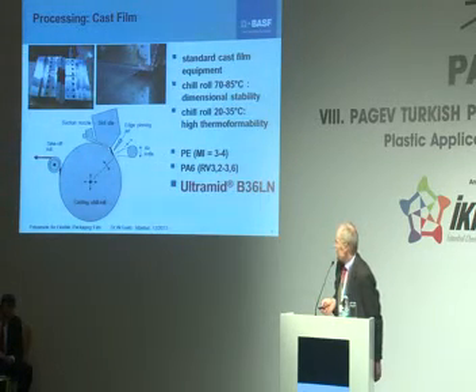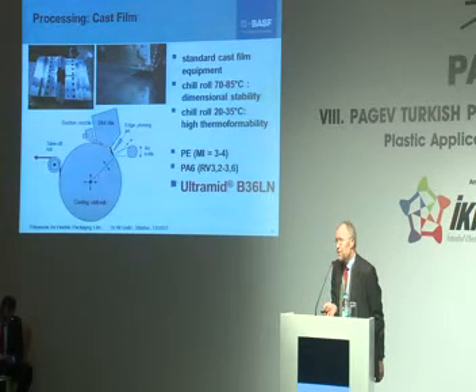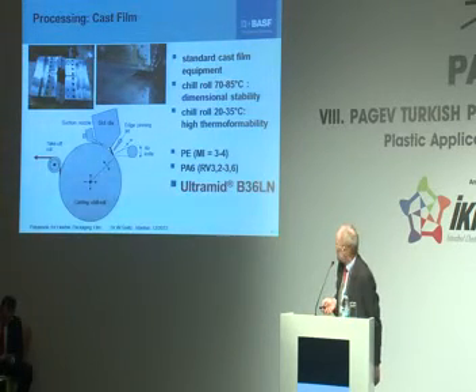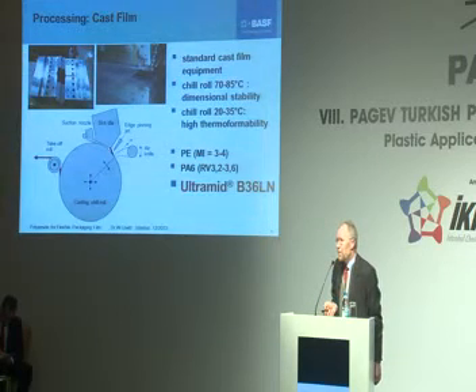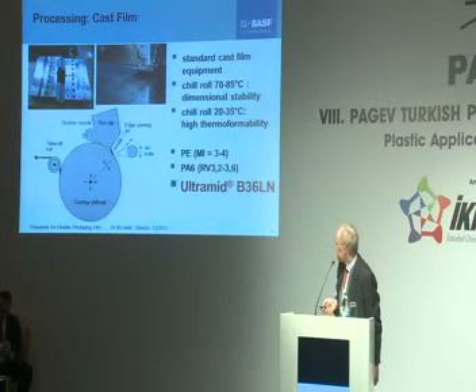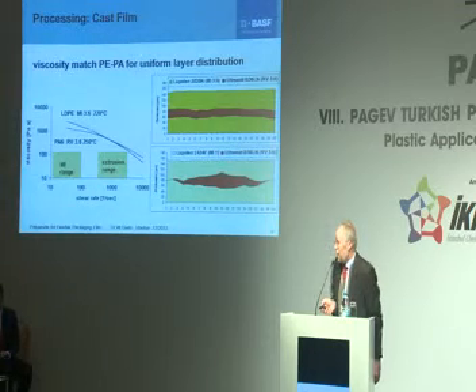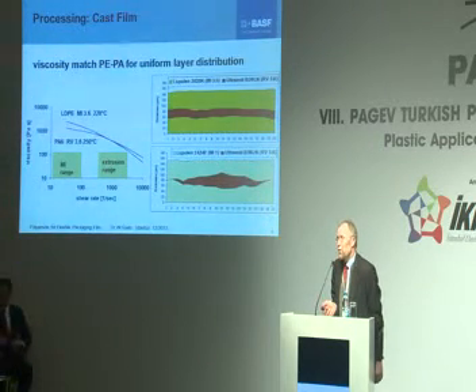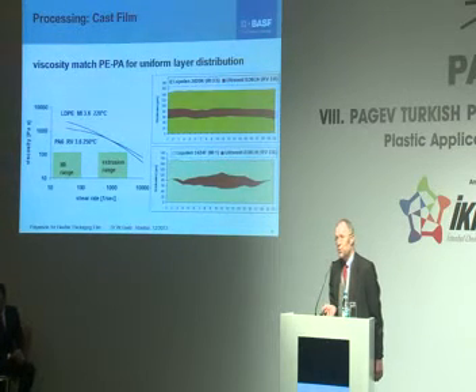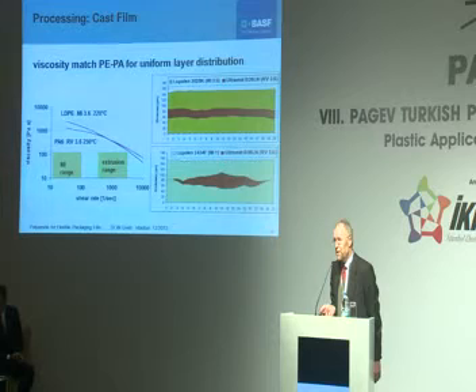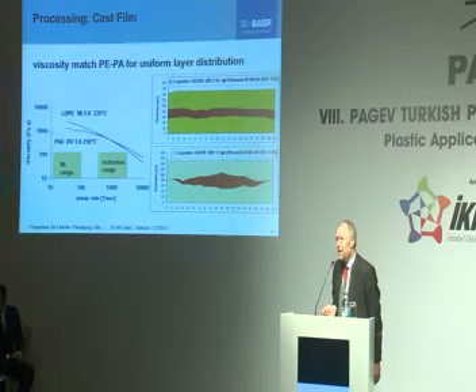By standard technologies, in cast film, the film is extruded on a chill roll, which may be at a temperature of about 20 to 30 degrees for soft thermoformable film, or at very high temperatures, even above 100 degrees for monolayer CPA lamination film. Important in the application of multilayer film is to have a viscosity match between the polyamide and the other components: polyethylene, polypropylene, EVOH, tie layer.